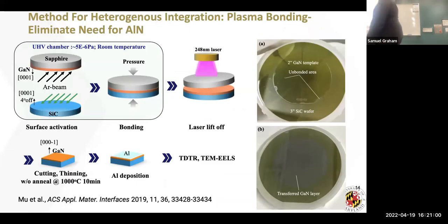There's a really interesting technique called surface activated bonding. This is the thing that we're doing with our collaborators in Japan. So I can take gallium nitride and grow it on sapphire. I can take my silicon carbide. I can expose them to this ion beam. It activates the surface. It breaks bonds. They become energetic. I can press these together, and lo and behold, they will stick. And then I can use a laser to basically laser liftoff, remove this substrate. This gives you a picture right here of this gallium nitride wafer bonded to a silicon carbide wafer.